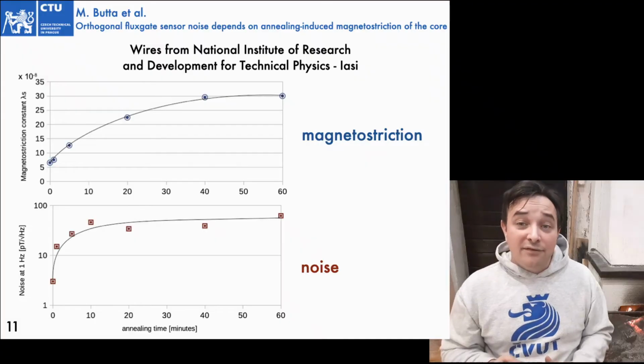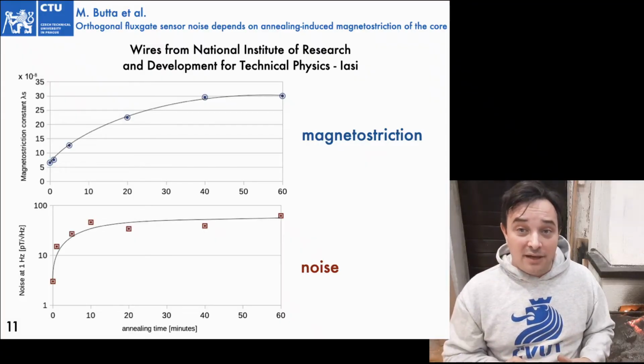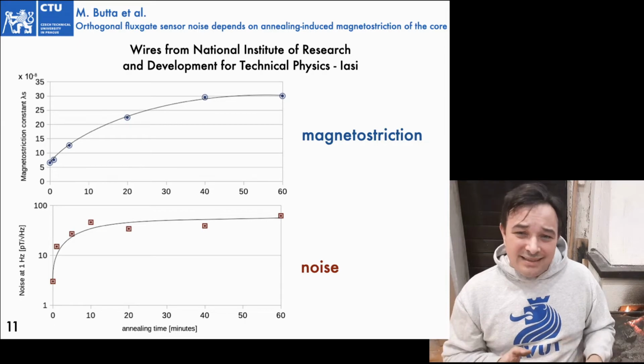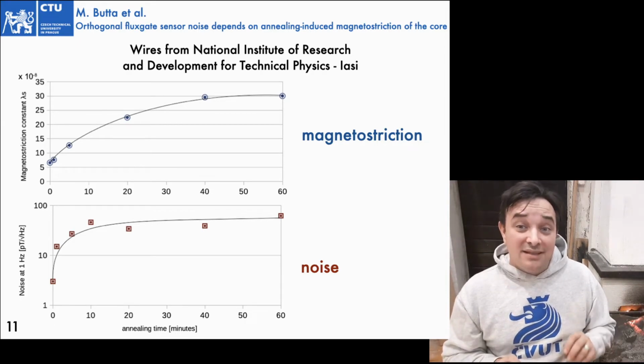We have to understand if really the problem of long time annealing is the magnetostriction of the wire, which increases if you anneal the wire for a long time. Therefore, we produced a sensor using another wire, a wire produced by the Institute of Physics of Iași in Romania. The composition is about the same, but in this case, the magnetostriction is slightly positive for as-cast wire.